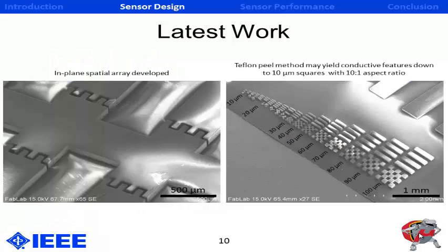These are some SEM images taken of devices made using the Teflon peel method. On the left-hand side, you can see there are 4 capacitor arrays. These are oriented in a 2D spatial array. And in this case, we have non-planar electrodes. On the right-hand side, you can see a series of conductive structures we refer to as resolution marks. These marks indicate how well the material was lifted off from the mold. It can create features down to 10 microns with an aspect ratio of 10 to 1, meaning it's 100 microns tall, but at a much lower yield than a larger structure, say, of 30 microns.